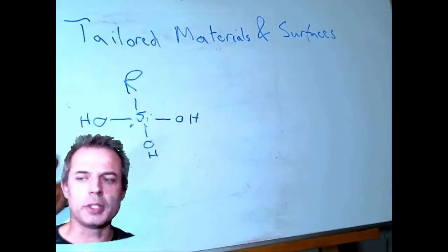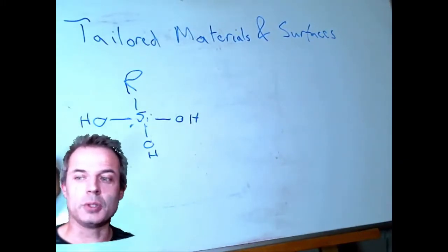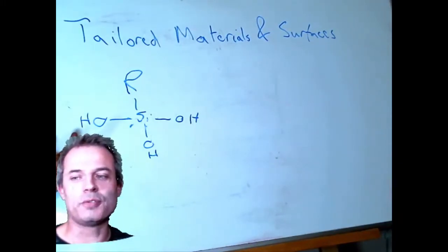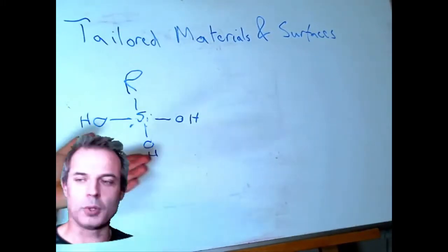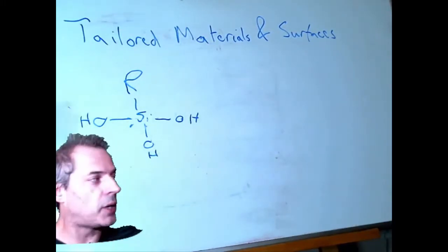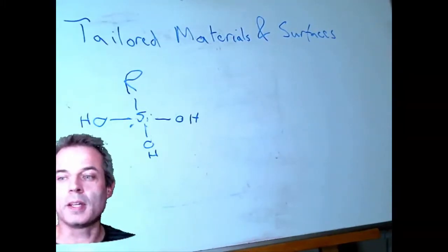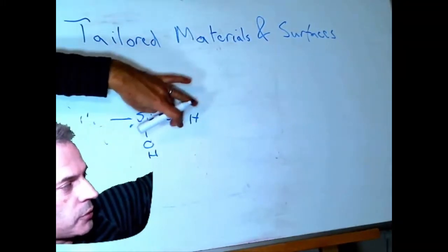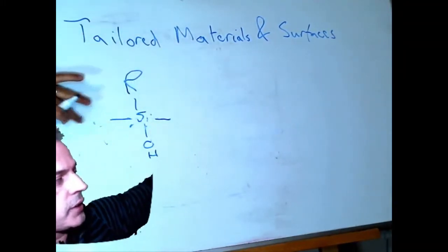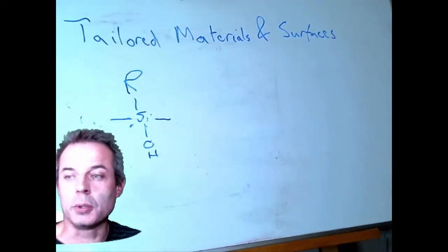What we usually do is we replace some of them and not all of them, and then they start to react with each other and with the surface. It's a much more ugly reaction than you would expect if you do this first. In reality, it starts to react with itself immediately to form oligomers, which is a bad thing about having multiple bonds. If we only have one, then it can't do that. So if I have two methyl groups and an R group, and I make this, then the most that I can make is the dimer, and the dimer can't do anything.